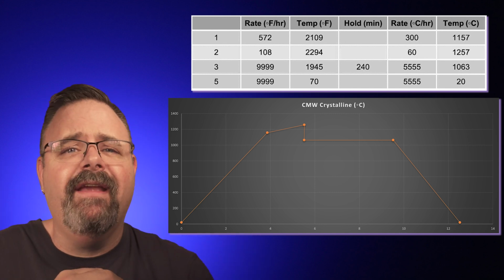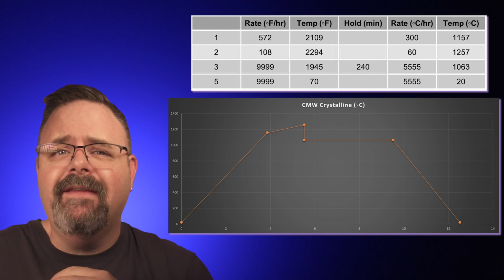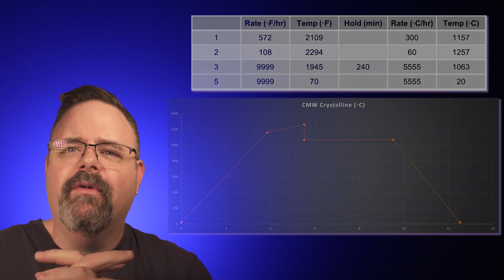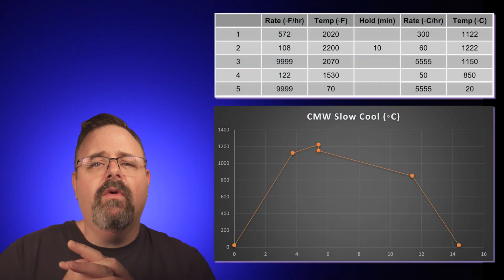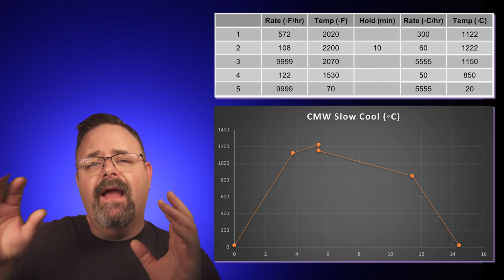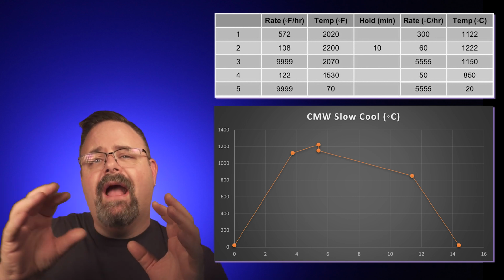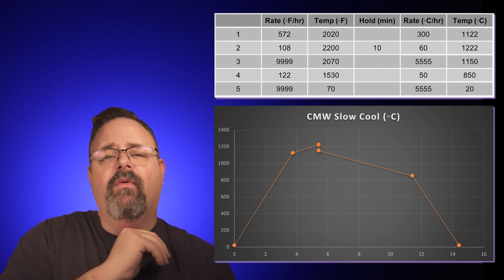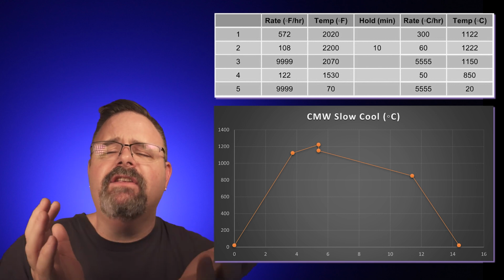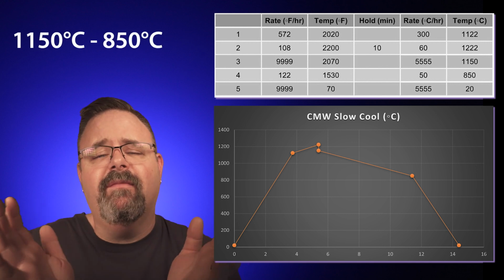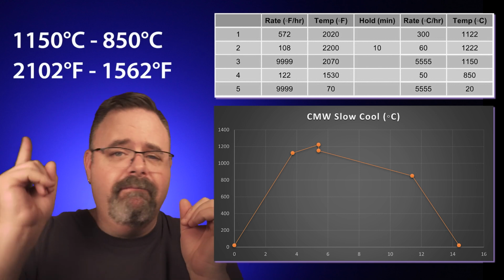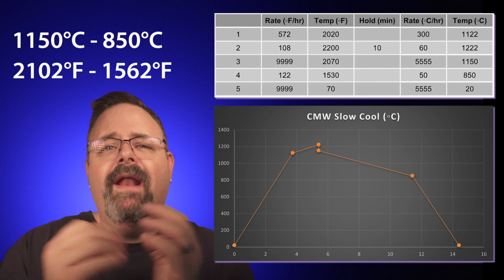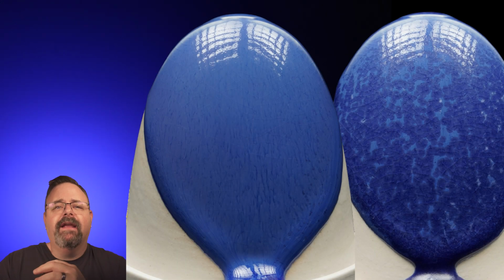And the longer that they hold, the bigger the crystals will grow. But for non-zinc glazes, those using calcium or magnesium, that's not how most people do it. What most people are going to do for calcium or magnesium crystalline glazes is do what's called a slow cool. And a slow cool is allowing the kiln to keep firing, but the temperature is gradually going down through that point where crystallization happens. And that's generally from about 1150 C to about 850 C, and this and that Fahrenheit. But whatever that is, that's when we're going to get the crystals to grow.